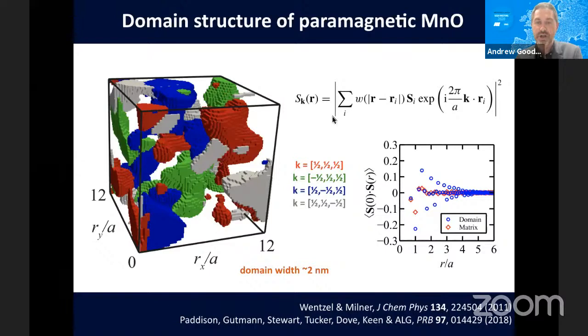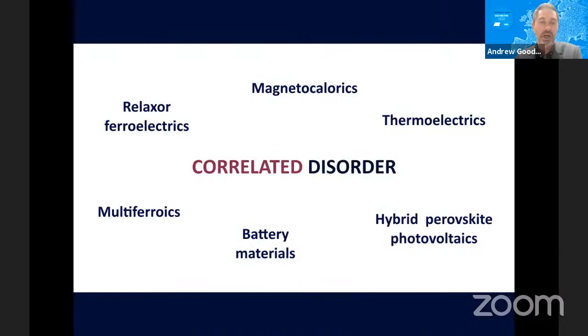So we can use these kind of local order parameters to probe that kind of local order. And indeed, you find that there are these domains that, depending on exactly where you define a domain beginning, are usually about 20 angstroms across, where you have quite strong antiferromagnetic order within those and a more disordered region in between, a matrix between, and you can interrogate all that. Okay, so more broadly speaking, what this is suggesting is that if you've got systems with some sort of correlated disorder, you can use scattering techniques to try and probe what's going on. And just to give you an overview from the materials chemistry community, there are lots of different really important materials where correlated disorder plays a role.